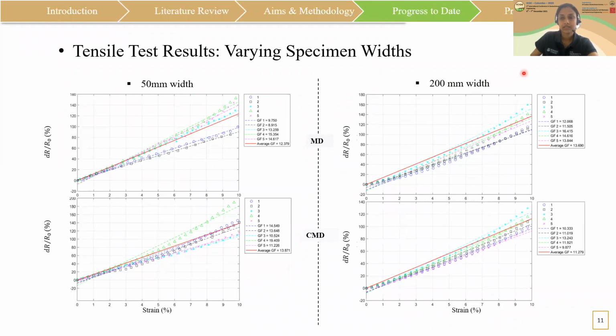Here I have given some results I got only for two specimen sizes, 50 millimeter and 200 millimeter width, for comparison. An average gauge factor was calculated for 5 repeated tests for each width per direction. It could be observed that the larger the sample size, the lesser the variability of the obtained resistance change results was. And the varying gauge factors along machine direction and cross machine direction indicated an anisotropic behavior in the resistivity of the material.